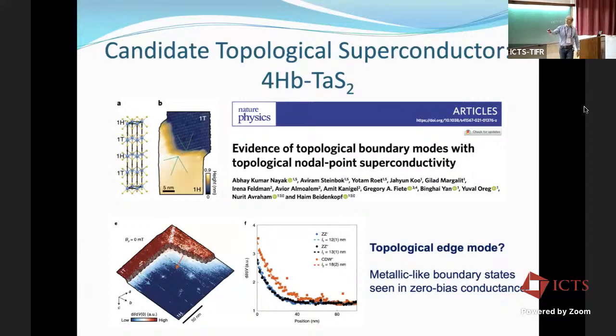This 4Hb is a much rarer compound, at least in terms of publications. It can still be grown. It's alternating layers of the 1H and 1T. So it's also a superconductor at low temperatures. A collaboration that I was involved with, focused within the Weizmann Institute, looked at scanning tunneling microscopy, STM, of this material.